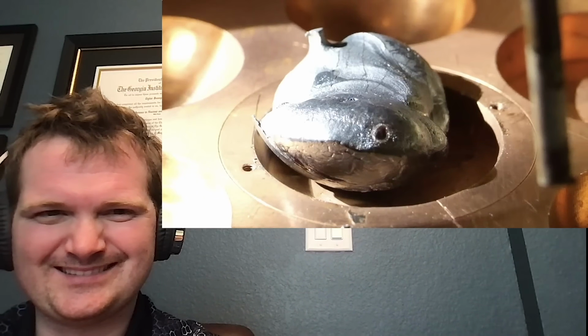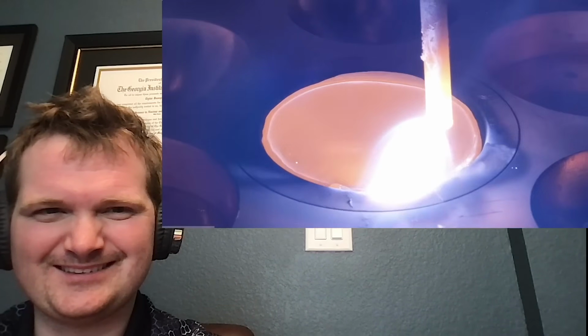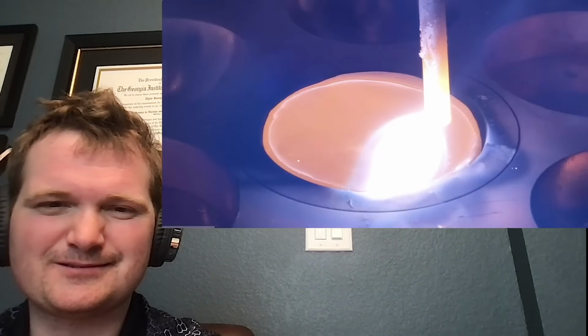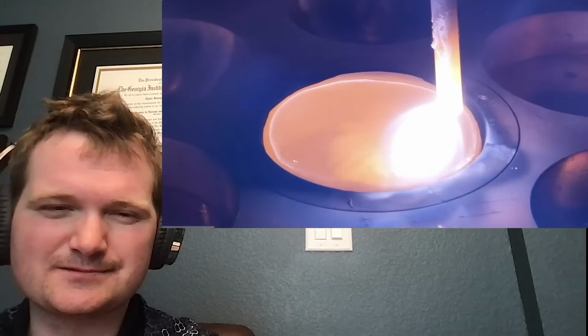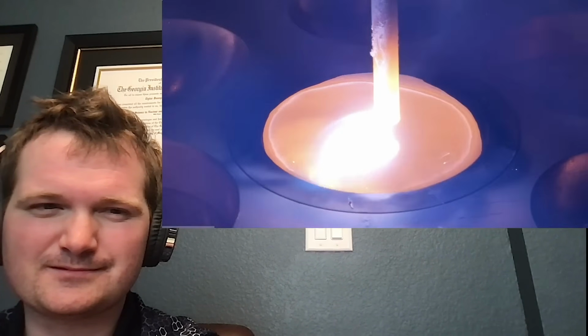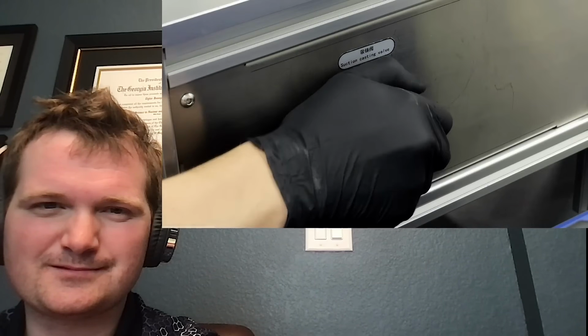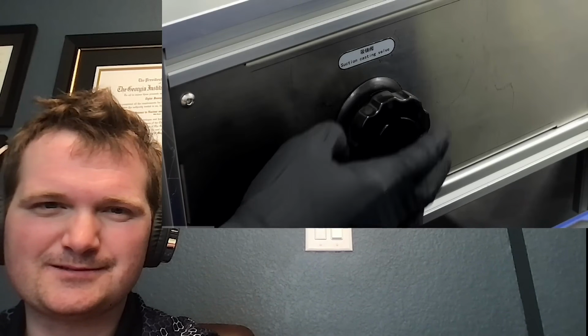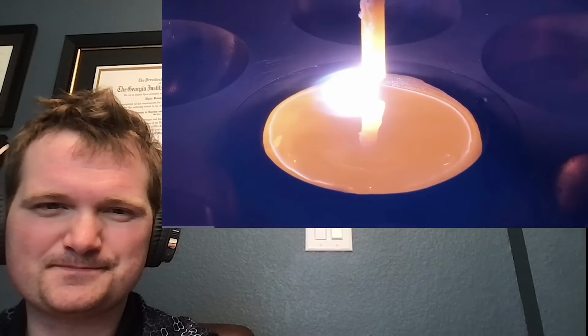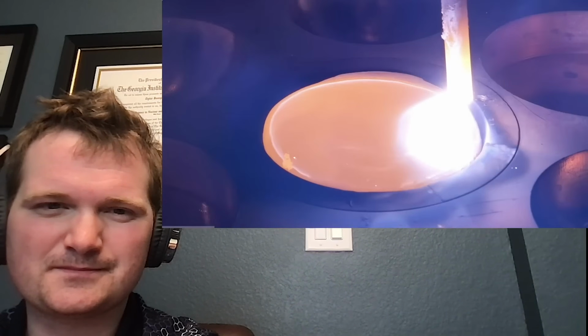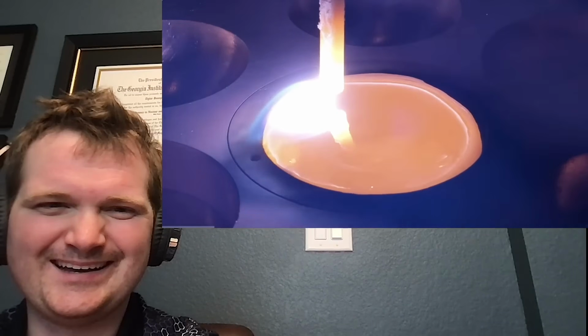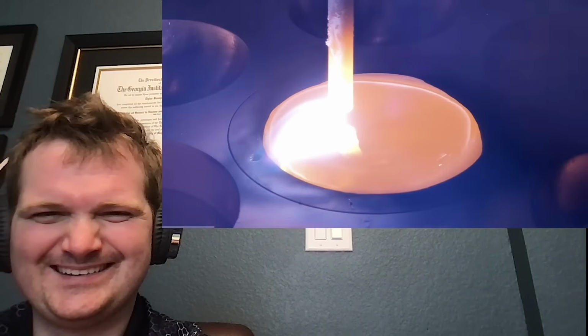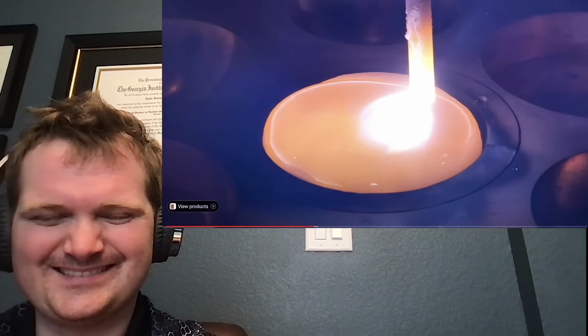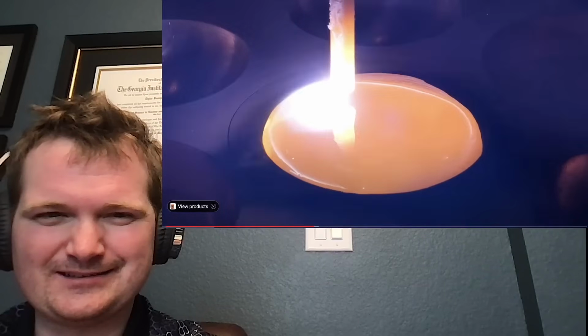I then sealed the chamber and cycled it like before, and I blasted it until it was completely molten. Now, to turn this red-hot metal into a hopefully beautiful disc, I apparently just had to quickly open this valve on the side and pull a vacuum. I then expected to see all of the metal to just quickly get sucked into the mold, except, well, absolutely nothing happened. It just sat there with seemingly no intention of going into the hole, even with the vacuum on full blast.